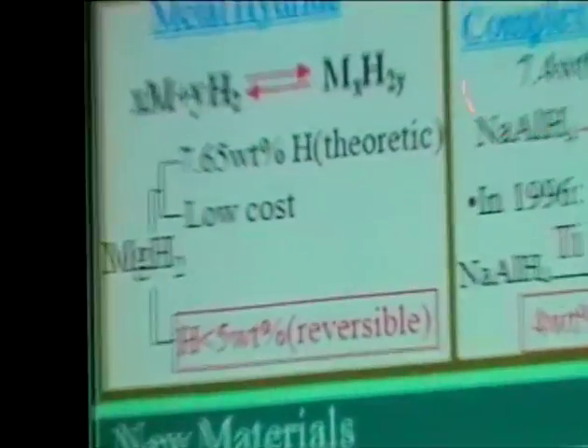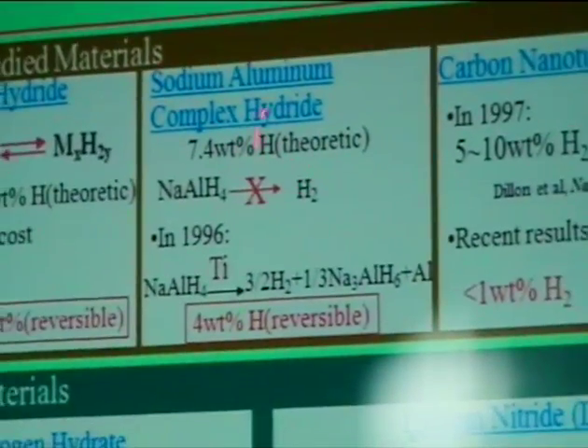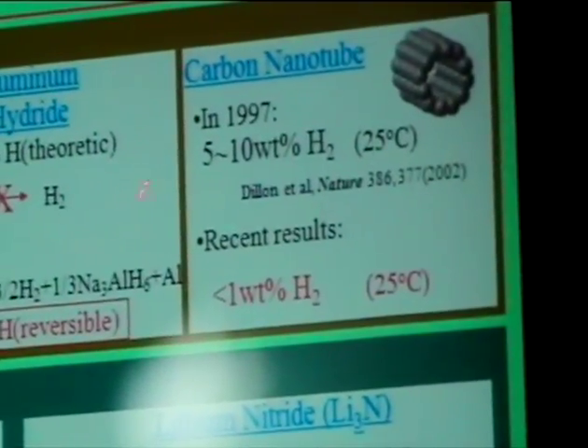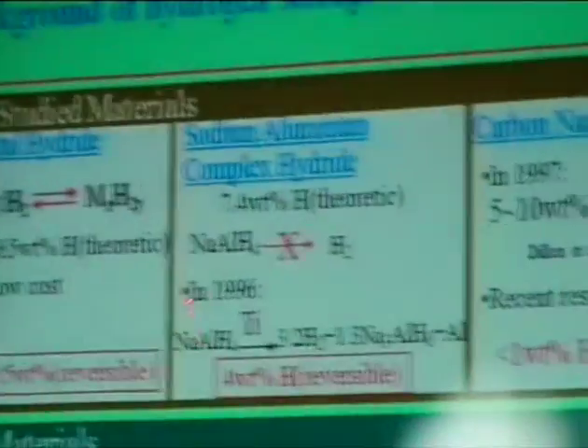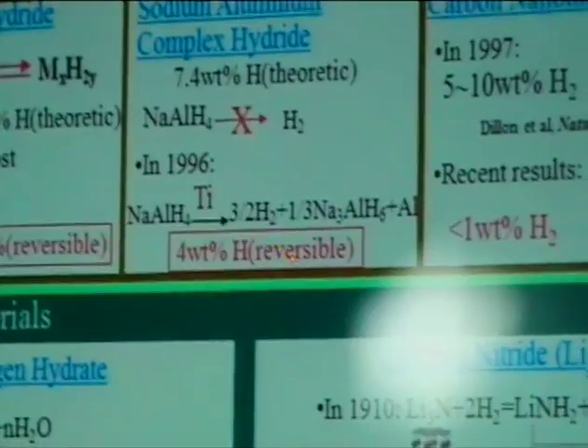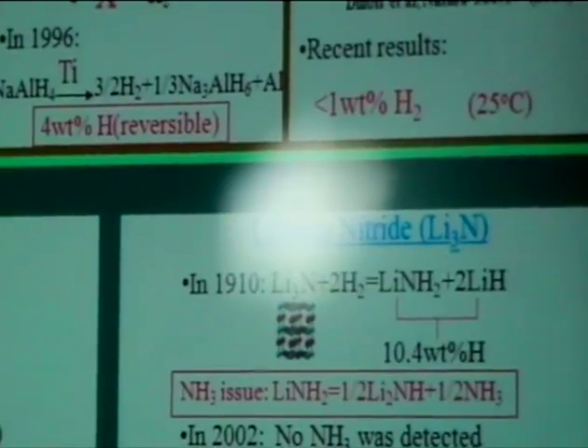The second one you can see is sodium aluminum complex hydride. That one can theoretically store 7.4% hydrogen. Unfortunately, that material cannot decompose to release hydrogen. But in 1996, a research group found that if you dope titanium into this sodium aluminum hydride, it can partially decompose to release hydrogen. So since 1996, the DOE put in a lot of money to commercialize this one. But unfortunately, they reached a conclusion in 2004 that it was not possible to commercialize it based on cost and capacity.